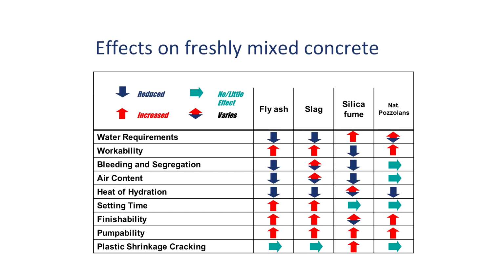So when you're adding these pozzolans to your mix, when you blend them in and formulate your mix, they're going to have different effects. And this is from the Portland Cement Association. It certainly doesn't cover all the pozzolans I use, VCAS is not on here, but you get a general sense of what's going on. So the water requirements for fly ash and slag are lower, silica fume much higher. I would say that if you add VCAS, your workability is going to increase just like slag and fly ash. Plastic shrinkage cracking, set time and all that are affected differently.